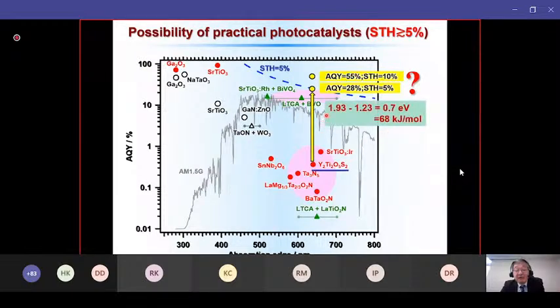Here I show a very simple calculation. The band gap energy of this material is 1.93 eV. And to thermodynamically split water into hydrogen and oxygen, it takes about 1.23 eV. So the remaining energy is 0.7 eV, or 68 kilojoules per mole. This is actually the driving force that we can use to improve the AQY or rate of the water splitting reaction. And we believe that this value is enough to improve our system to this region. So we are now focusing our effort to achieve these values in the near future, hopefully in a few years.